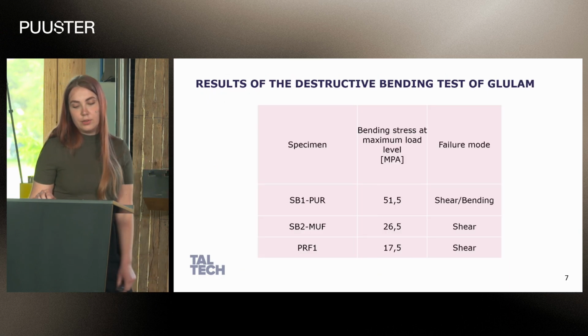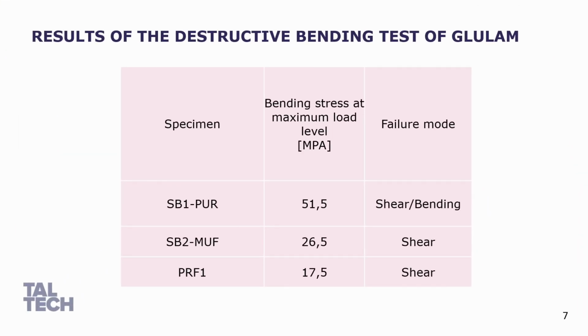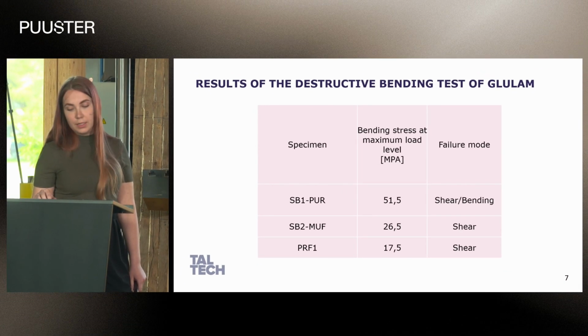And here are the results of the destructive bending test, which were carried out on 3 glulam beams, all bonded with different adhesives. Unfortunately, none of the beams reached their maximum bending strength, as all of them failed primarily due to shear failure. A slight bending failure was observed in the glulam beam bonded with the PUR adhesive, although it was not a critical factor.